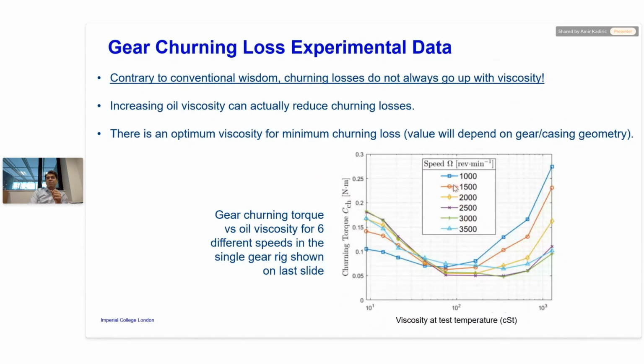And these are different speed curves. So if you just focus on one speed, let's take the high speed, 3,500 RPM here, you see that initially as the viscosity increases, the churning loss drops. Indeed, it starts going up after a while, but initially it drops. So there's an optimum viscosity in terms of minimum churning losses. Now, that will be casing dependent. And you might wonder why that makes no sense. The more viscous the oil is, the higher the churning losses are. Not true. And other people have seen the exact same thing.